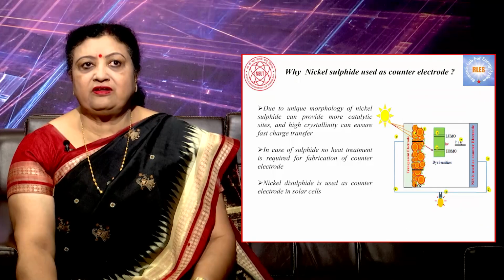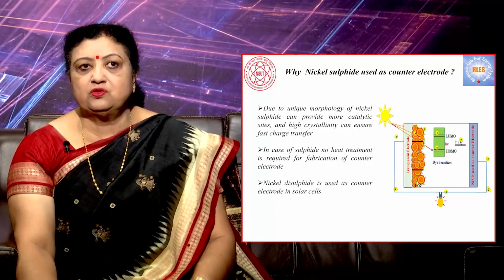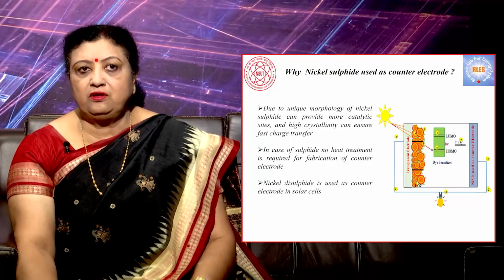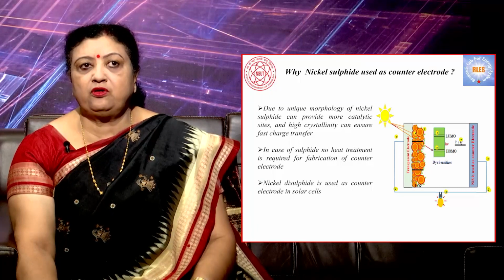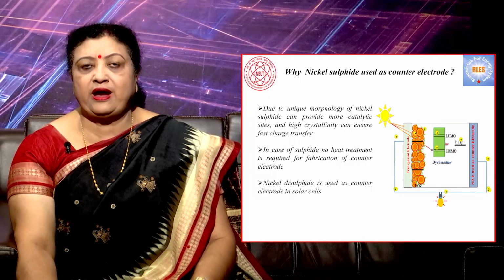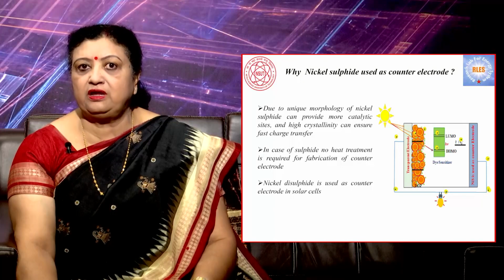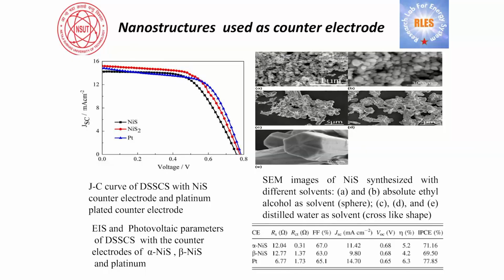Nickel sulphides can be used as a counter electrode, and due to the unique morphology of nickel sulphide it can provide more catalytic sites, and high crystallinity can assure fast charge transfer. In the case of sulphides, no heat treatment is required for fabrication of the counter electrode. Nickel sulphide is used as a counter electrode in solar cells. Nanostructures used as counter electrode.